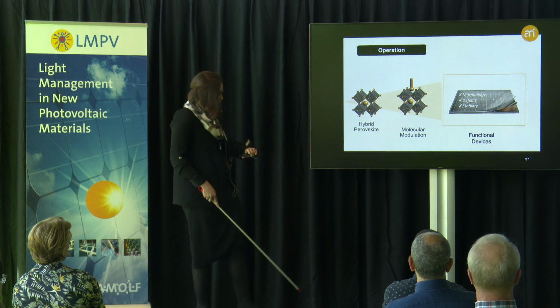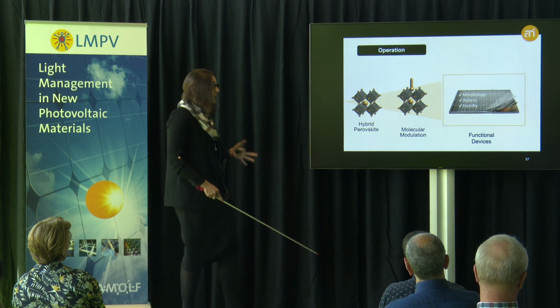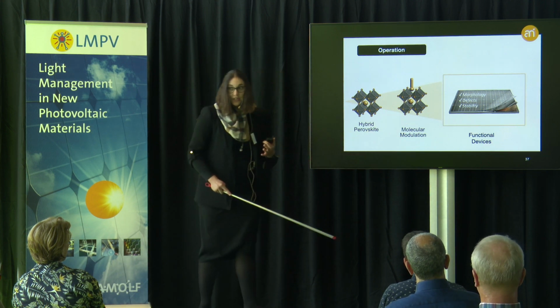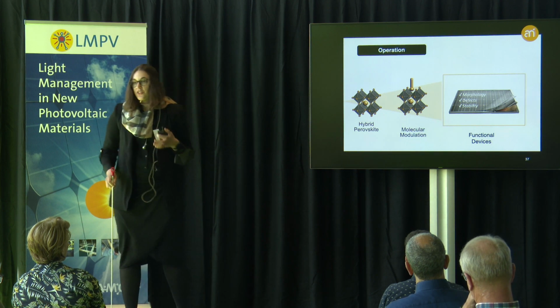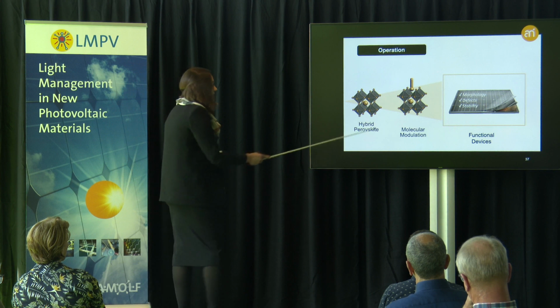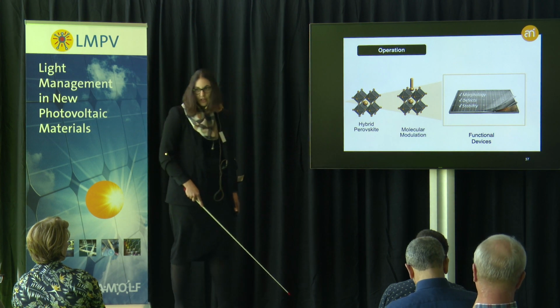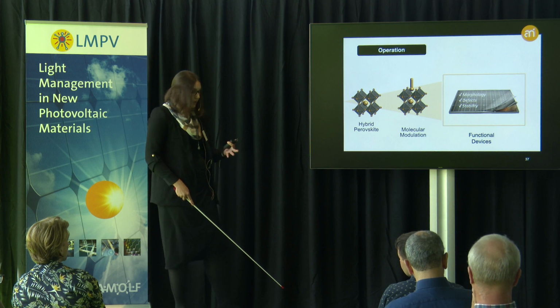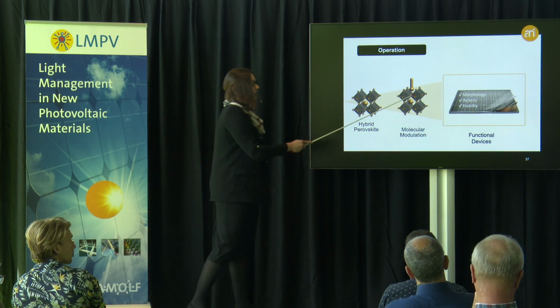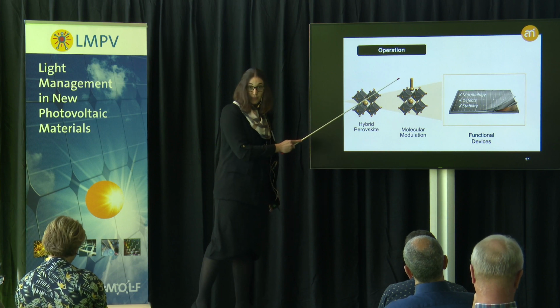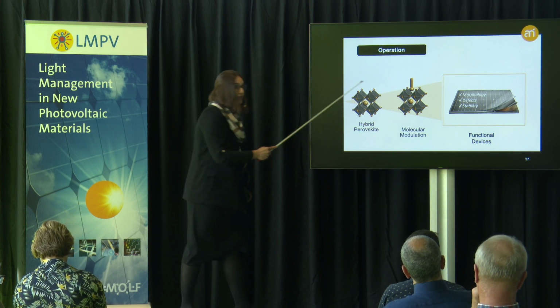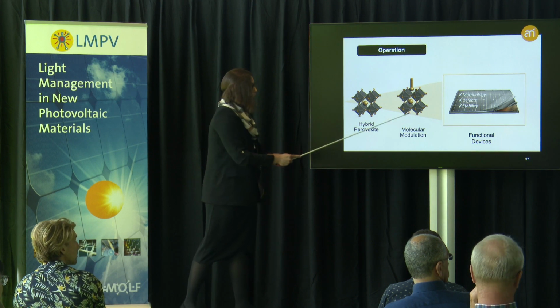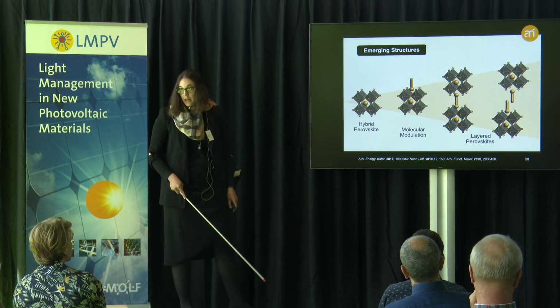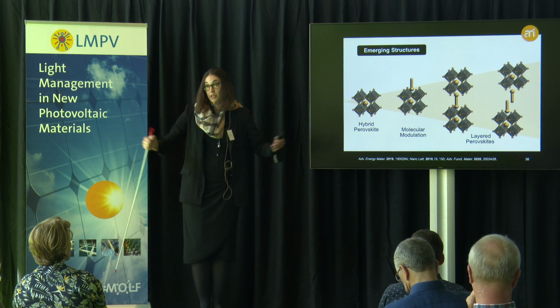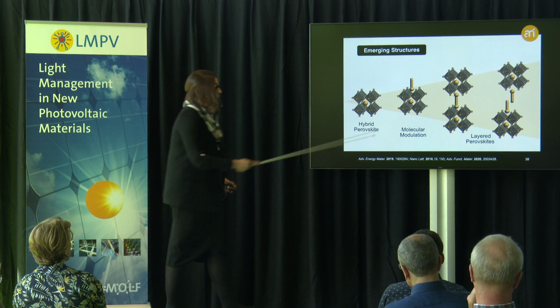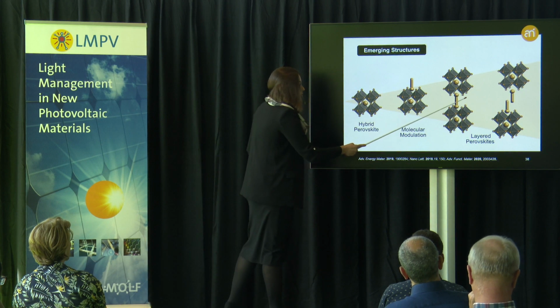Now, this illustrates the capacity of supramolecular engineering in the context of not only crystal engineering and controlling the morphology, but also the defect chemistry, as well as the stability of these systems through these intricate understandings of the atomic level interactions, which now open the path for taking a step beyond the use of these small substoichiometric amounts of molecular modulators at the surface of hybrid perovskites to fully incorporating them within the extended perovskite architectures in order to build extended hybrid materials, where the organic component plays a role within the hybrid perovskite structure by templating